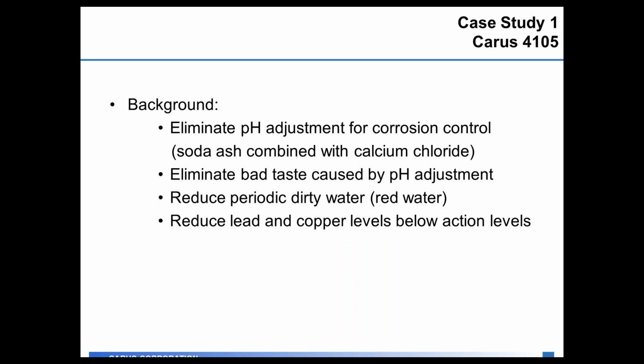So the first case study we have here is on Carus 4105, and the background of this plant was they were using pH adjustment for corrosion control at this plant. And what they were using was two products. They were using soda ash and they were combining it with calcium chloride. What they were getting was consumer complaints in the distribution system from a bad metallic taste to the water caused by the addition of the calcium chloride and the soda ash. They were still getting some periodic dirty water, red water complaints from iron corrosion in the system, and they were still having issues with the lead and copper levels being above the action levels, so they wanted to reduce those numbers as well.